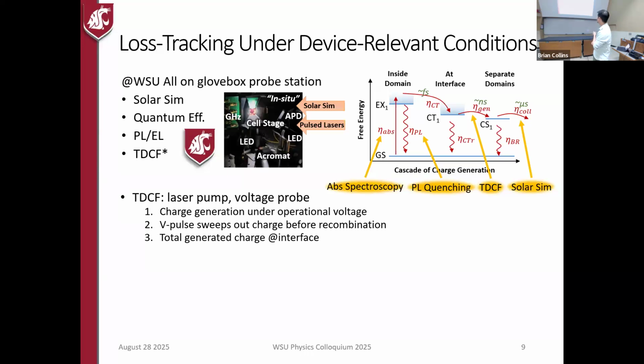And then before any bimolecular recombination can happen, you extract the charge with a voltage pulse. So that has to happen between the nanoseconds and microseconds. And so what that gives us is the total generated charge at the interface. So when we put all these together, we can quantify basically the efficiency of each step in a particular cell.